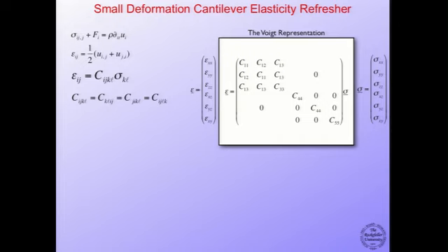Okay, so in order to do this, you need to set up a simple bending system that you can turn the crank on the elasticity to get somewhere with. You want to relate the stress and the strain. You don't need to do the whole fourth-rank business because of the Voigt representation and the symmetries of the compliance tensor, so you can cut things down considerably at the first pass. Even better, as it turns out, you don't need to. This is the compliance tensor in the Voigt representation for a full uniaxial symmetric solid, right? It has five different possible independent entries.